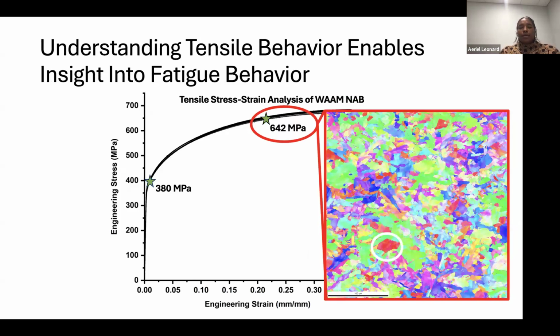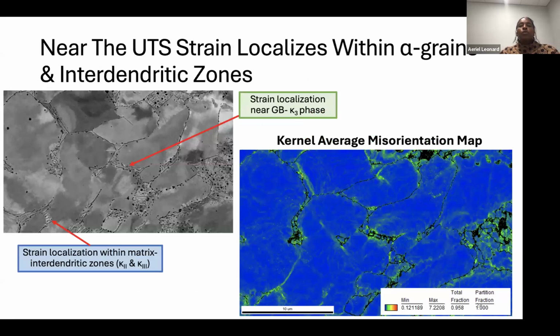And so then what we really wanted to see was, okay, as we progress to higher levels of plastic strain, what is happening in the microstructure? So we used EBSD to really see where we had a grain that we knew had multiple slip systems that were active in the material. One of the things we wanted to see was where is strain localizing? So we use EBSD, of course, to look at how the orientation was changing from region to region through the kernel average misorientation technique. What we learned is that the majority of what we're seeing is strain localization within the alpha grains, which isn't hard to believe. I showed you some of the stacking fault formation and planar slip in the grain, but then also along these interdendritic regions where we know we have Kappa 2 and Kappa 3, there were high levels of misorientation.